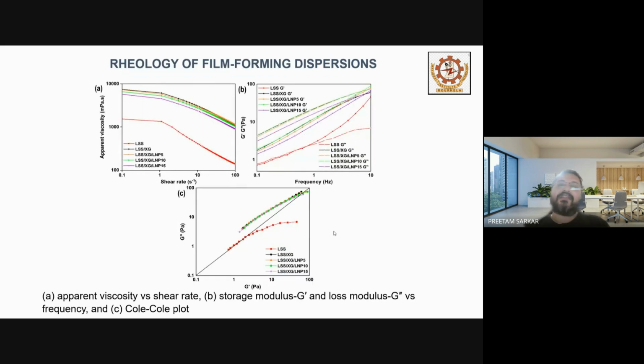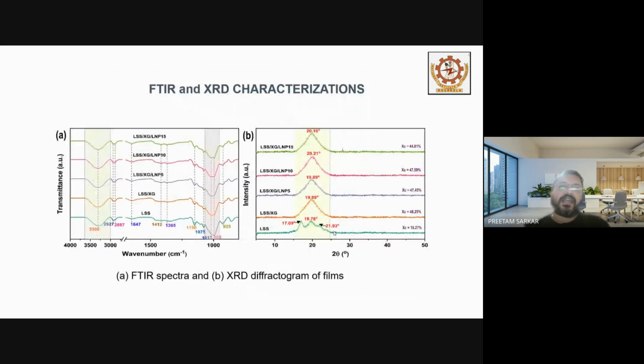Then there are standard engineering techniques called rheology, because to form the film, first we have to prepare the emulsion, and from the emulsion we go to the film. So we have to characterize some properties of the emulsions, which we study using a rheometer. Then we do the basic molecular level characterizations, FTIR and XRD. FTIR will give us the functional groups and functional properties of the films, and XRD will give us the crystallinity and amorphous nature, how much is crystalline and how much is amorphous, of the films.